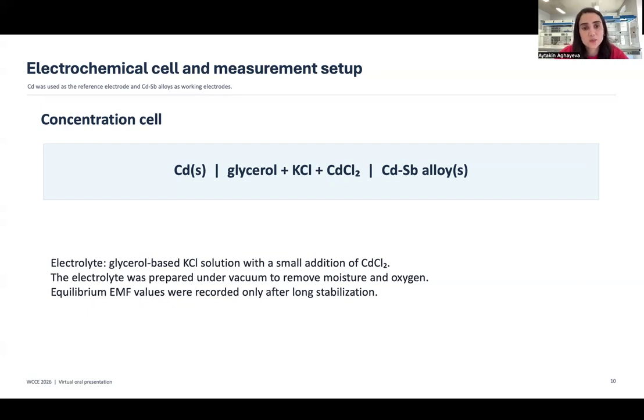The electrolyte was based on glycerol, potassium chloride, and a small amount of cadmium chloride, which provides cadmium ions in the electrolyte. The electrolyte was prepared under vacuum to remove moisture and oxygen, because these impurities can affect EMF values. EMF values were recorded only after long stabilization, when the system reached equilibrium.